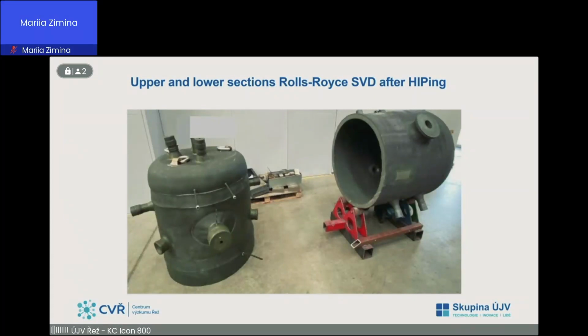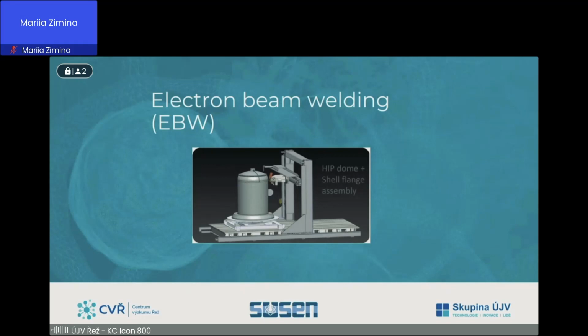The other very important technology for production of components for the nuclear industry is electron beam welding. Electron beam welding is a joining process that is commonly performed under high vacuum, approximately 10 to the minus 4 torr, in a suitable chamber. The chamber prevents scattering of the electron beam during the welding and shields the high energy X-rays emitted during the process.